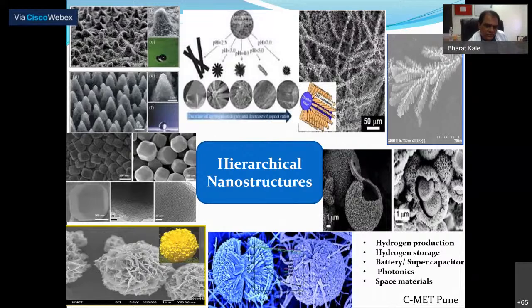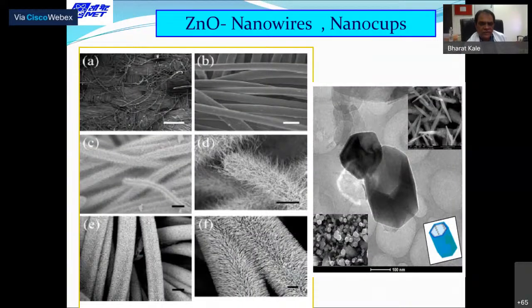These are the structures we make for many applications. This is ZnO nanowires. There is a secondary growth of this. Initially you can have ZnO rods with hydrothermal reaction, and then again do a sonochemical or hydrothermal reaction further with a growth directing reagent. We can have this kind of dendritic structure. It's very good for sensor applications.